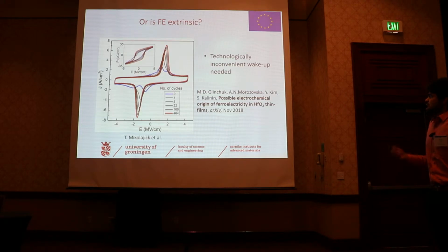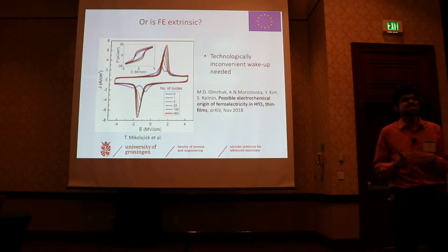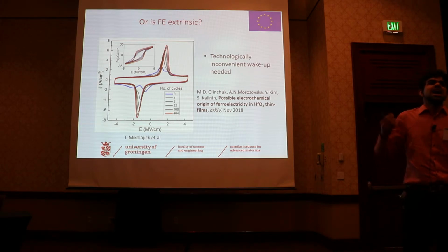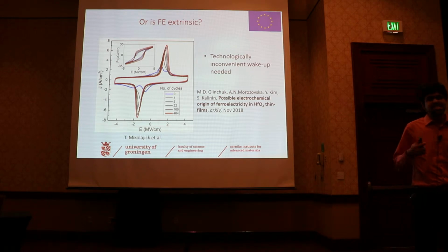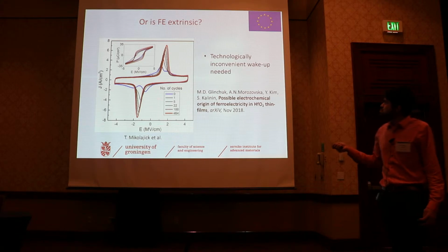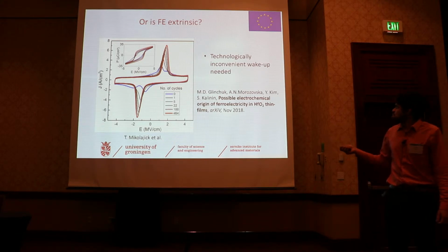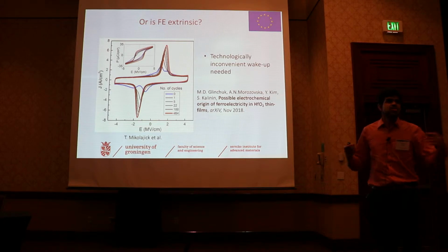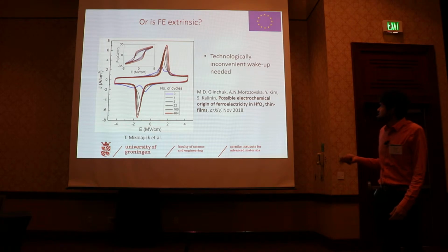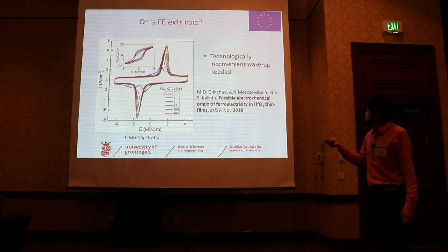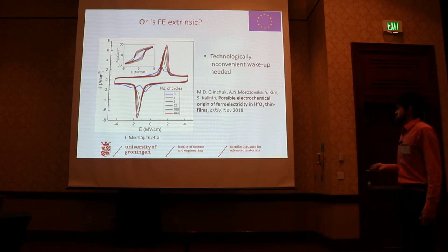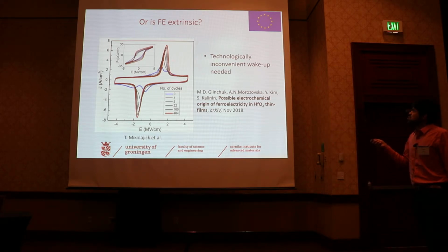Right? Okay, but since these are multi-grain polyphase films, it's not very clear whether this is the only phase that is responsible for ferroelectricity. Is it intrinsic, or are there other extrinsic effects? For example, all these films show what is known as the wake-up effect. In the first cycle of switching, they don't really show any significant ferroelectric switching of polarization up to polarization down. You need a certain number, in this case let's say 500 switching cycles, to stabilize the polarization while switching. So this is the so-called wake-up effect.